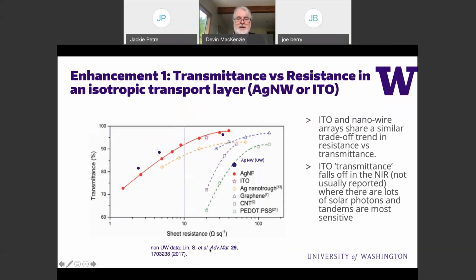This is a plot here. I'm showing typical stuff out there, the merit of CNT in terms of sheet resistance and transmittance. Here's the ITO. We want below 20 ohms per square and about 90%, and that is the ITO range. With these silver nanowires, we show we can actually get there, but at very low temperature.